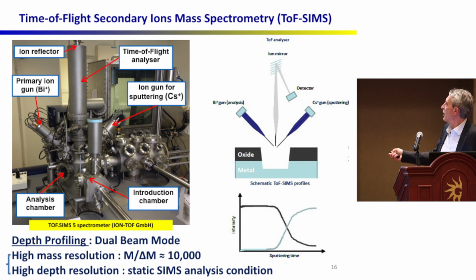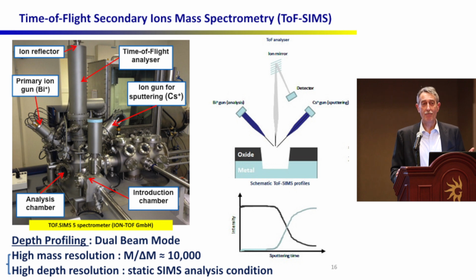So we can record for any species the intensity as a function of depth. And because we analyze the mass, we can use isotopic markers. This has been done in the past. We were not the first to use isotopes. For example, in the corrosion community, Mike Graham and his group used oxygen-18 a long time ago with static SIMS. But now we have the time-of-flight SIMS, and what we did, which had not been done before, is that we implemented on the time-of-flight SIMS the possibility to do in situ oxidation with either oxygen-16 or oxygen-18.